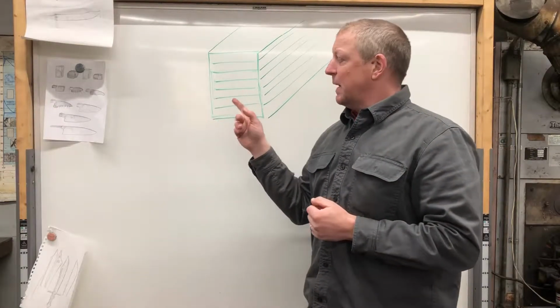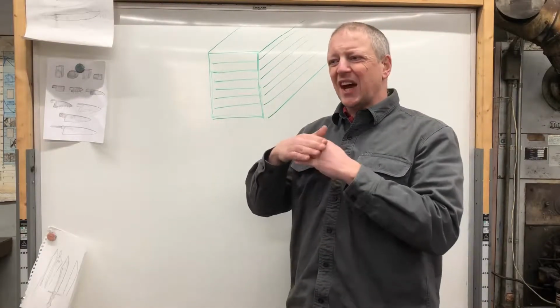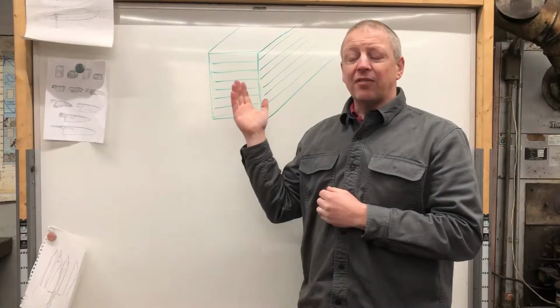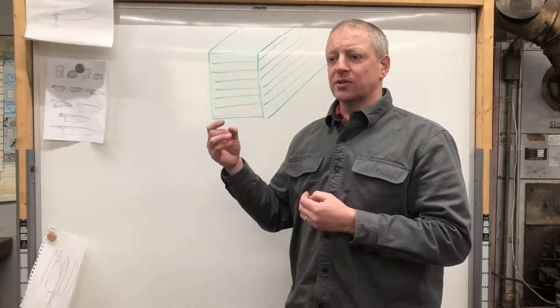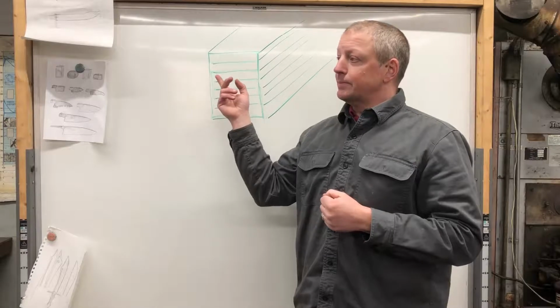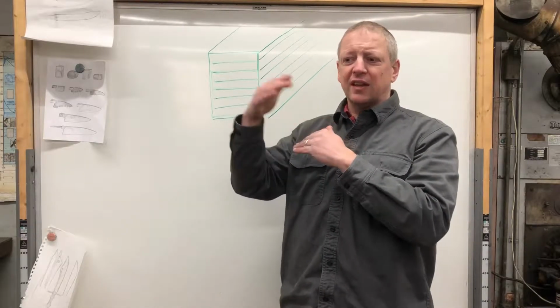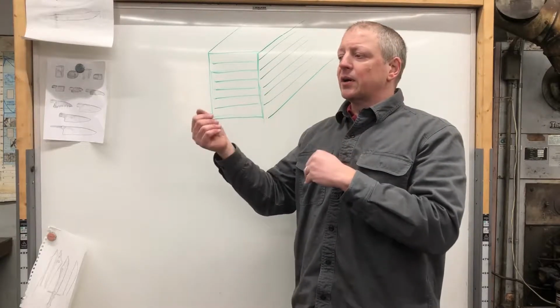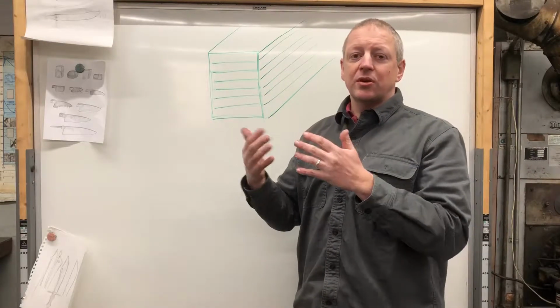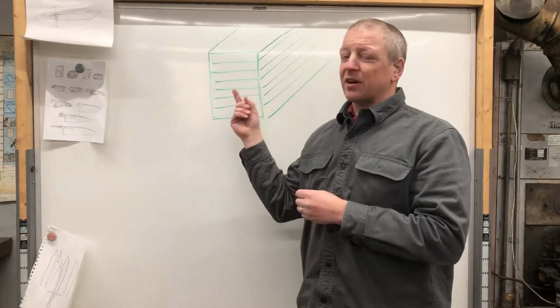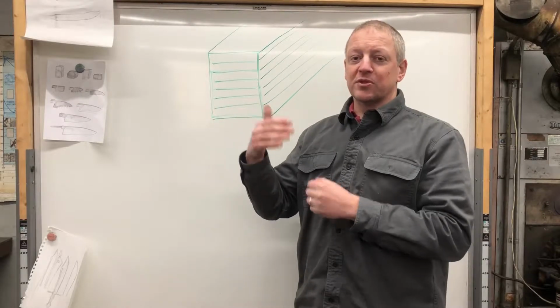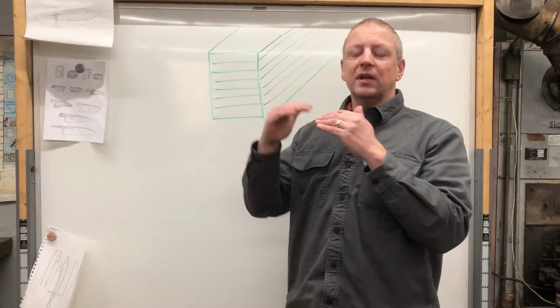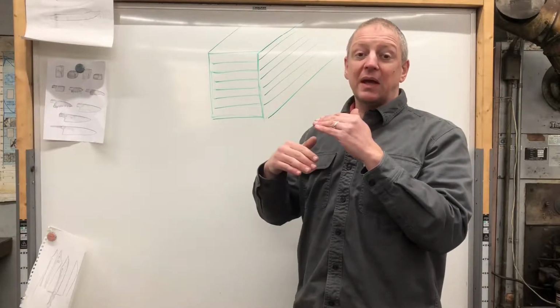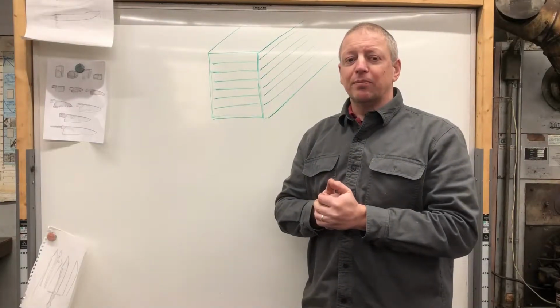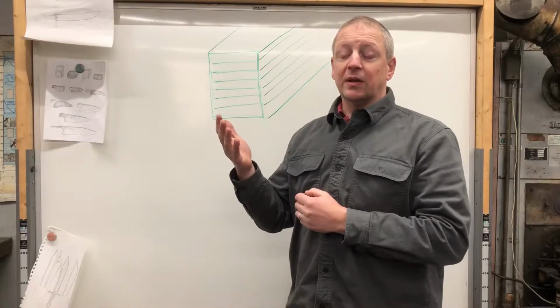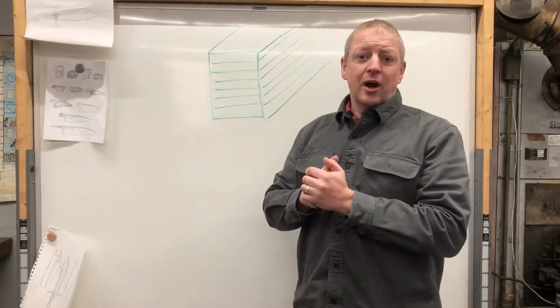Another point here that I should make is that the normal tight oxides that you would have on steel straight from the mill, maybe not hot rolled steel, but cold rolled steel certainly, and to a degree hot rolled steel, are tightly adhered to the surface, so you could say that they are chemically continuous. Therefore, carbon migrating out of the steel can reach those oxides and they float away. However, loose oxides that have become separate from the surface, or where you have such a thick layer that carbon's going to make it to that first layer, not really easily make it through, those oxides are not going to be readily broken down by this process. Certainly carbon or oxide that is not attached to the surface, how's the carbon get to it? Can't do it.